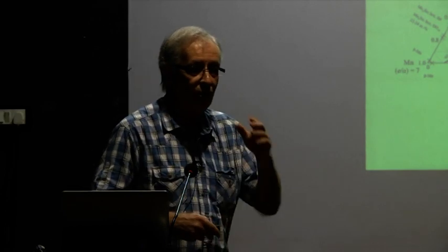We have here nickel-manganese 50-50. It has an L10 structure. It's tetragonal. And then we have the L21 here, which is cubic. So if we go along this line, we should be transforming from an L10 to some cubic structure. Okay? And in the course of this transformation, it may be that we encounter a martensitic transition.